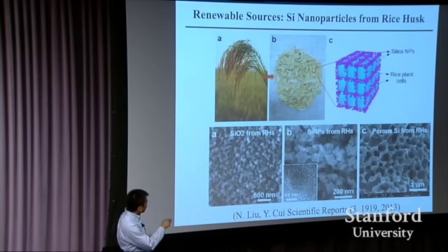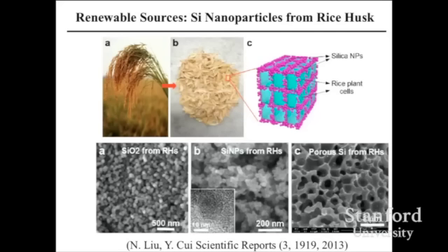Actually, research doesn't stop right there. With silicon, we are influenced by what industry really needs. If you ask the question, you want everything low cost, can you make it happen? For example, silicon nanoparticles are not low cost enough. Nan is a graduate student in the group. Looking into this, it turned out rice husk, this waste, has a lot of silicon dioxide in there, already distributed at the nanoscale. 20% of the weight of the rice husk, you probably didn't recognize, is silicon dioxide. If you burn these organics away, you produce beautiful silicon dioxide nanoparticles, reduced by magnesium, a low-cost metal, becoming silicon nanoparticles. You can generate porous silicon as well. This is a starting material to do scale-up synthesis.